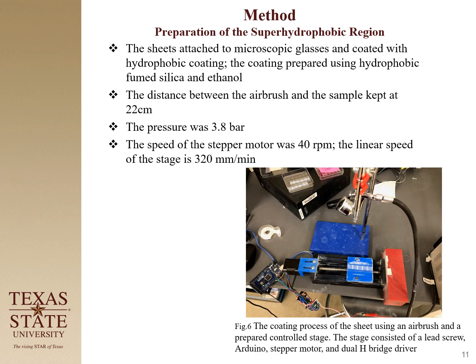Next is coating those samples, because those samples after printing are hydrophilic, and I'm here making the superhydrophobic region. So I attach those sheets onto a glass, and then I made an apparatus which consists of a controlled stage, stepper motor, and Arduino, and I control the speed of the movement of the stage, and I use an airbrush to coat my sample. Of course, I made my superhydrophobic coating using fumed silica and ethanol.